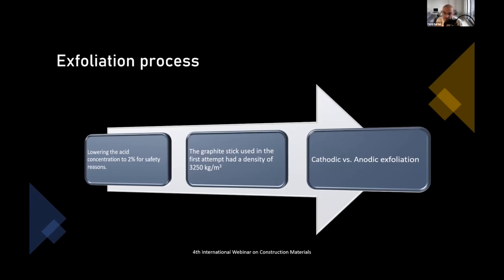In addition to that, we have tried to test another graphite stick with a lower density of 2,540 kilograms per cubic meter. We applied 12 volts DC current again, and this stick had completely exfoliated into graphene oxide after 24 hours. The next step was to excel the quality of acquired GO, that is graphene oxide, via the means of ultrasonication.